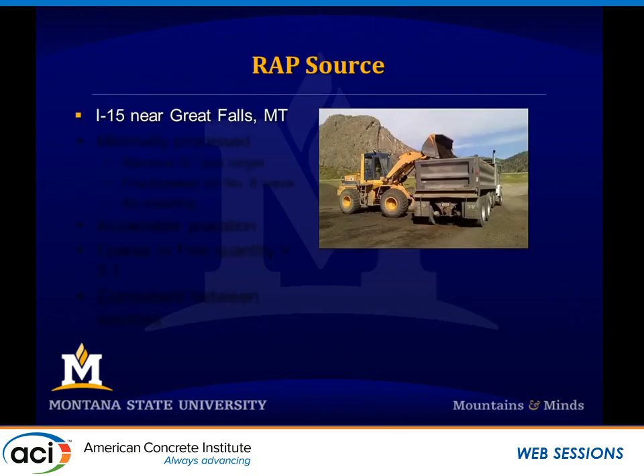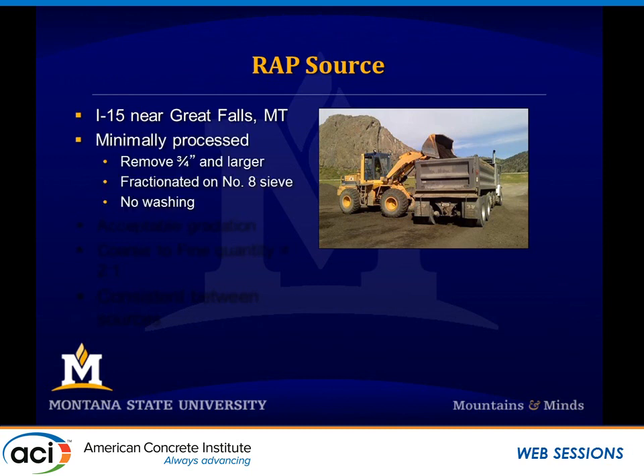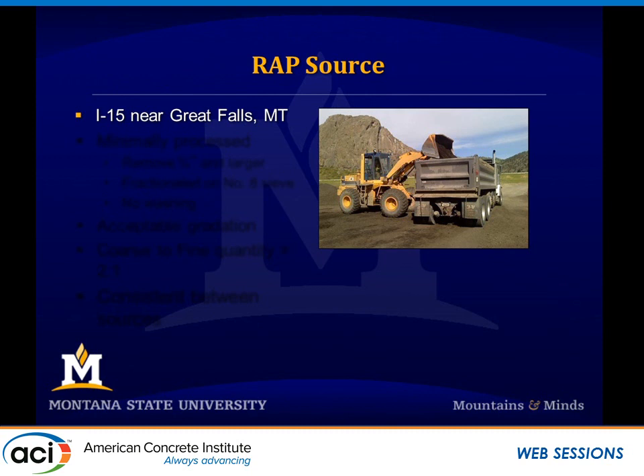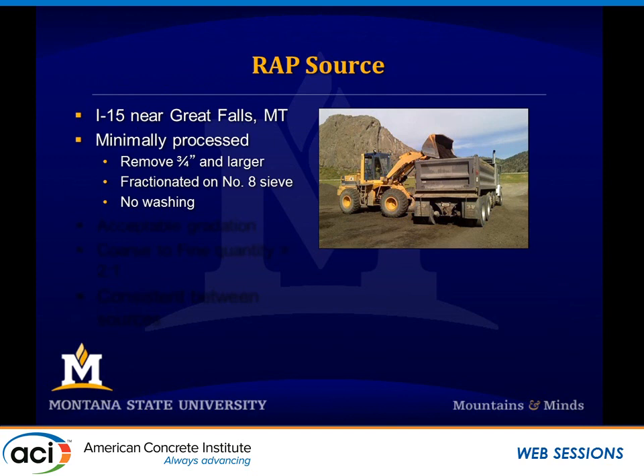So the first thing we came up with was establishing a RAP source and coming up with a processing technique that was minimal. So all this research was conducted with RAP millings off of I-15 near Great Falls, Montana. It was minimally processed. What I mean by minimally processed, we just took the RAP millings directly out of the miller, and then we screened it on 2 different screens, a 3/4 inch screen and a number 8 screen. Everything above 3/4 that was caught on that was tossed out as waste, just big chunks of tar and whatnot. Everything that got caught on a number 8 sieve we called coarse aggregate. Everything that made it through the number 8 sieve we called fine aggregate. And we did not do any washing of the aggregates afterwards.